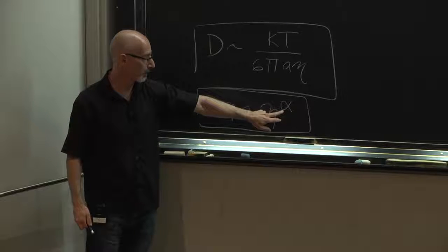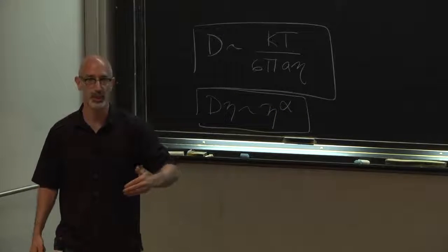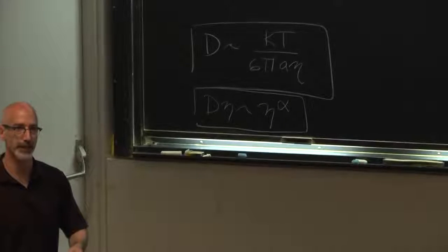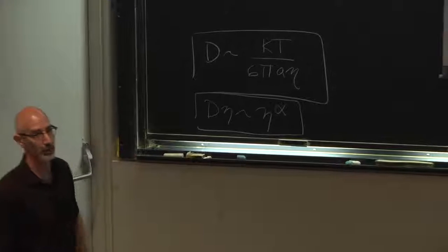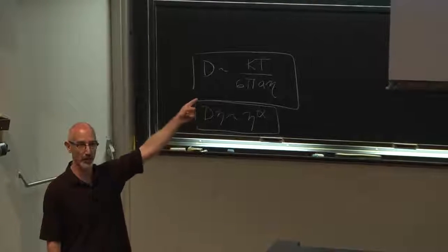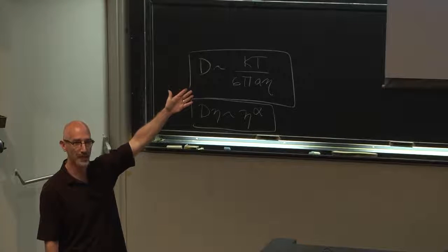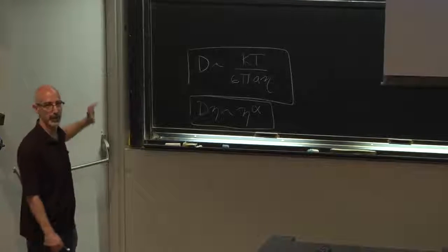But if alpha is larger than 0, then the difference between what you would expect in terms of the effective diffusion constant or the effective viscosity from the Stokes-Einstein relationship, as you get closer and closer to the glass transition, may be a few orders of magnitude different than what you actually measure. In particular, the diffusivity of the system may be 2 orders of magnitude larger at or near Tg than you would expect from just measuring the viscosity and using the Stokes-Einstein relation.